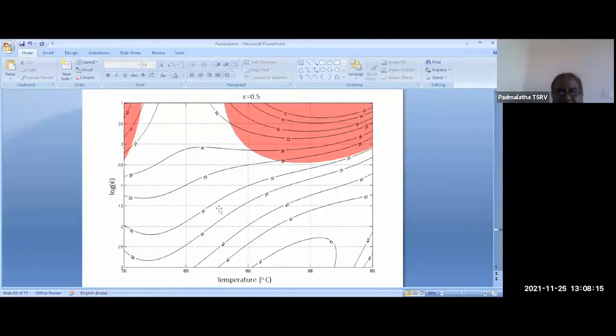So these are our domains. At what temperature and what strain rates is the material safe? The shaded region is the instability region. When you work in this region, the material is unsafe. It means there is a possibility that some dislocation bands may occur, some deformation bands may occur, some flow localization may take place, some cracks may occur, anything may happen. So it is showing both the unsafe regions and safe regions. In the safe regions, we can see that the efficiency is a maximum of 47%, and in unsafe regions the efficiency is very, very low.